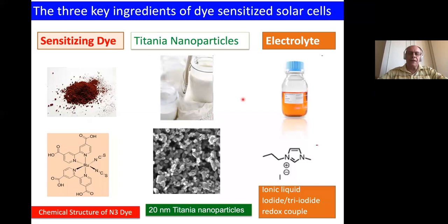Interestingly enough, almost the very first materials used stood the test of time very, very well. So this is the TiO2 material. As I said, you can see it as a nano sponge. This is the top view, and it's porous all the way down to the contact. Here is the dye molecule, and this is a very classic one, which was the state of the art, the best for more than 15 years, developed in Grätzel's lab.